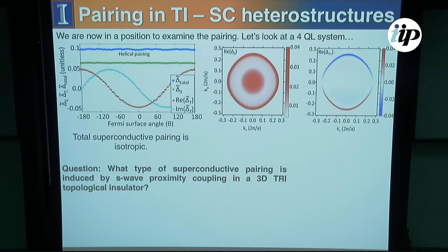And we can also look at the in-plane components of the superconducting order parameter, and we can see at the edges, of course, we have the S wave. So this is my S wave components. This is my S wave surface state, and then I have the S wave bulk states, and then beyond that, I also have my P wave states. These are doubly degenerate bulk states, so I'd expect there to be singlet pairing there. The surface states are not doubly degenerate, so this is why we see the P wave accumulating in the surface states, but not in the bulk states.